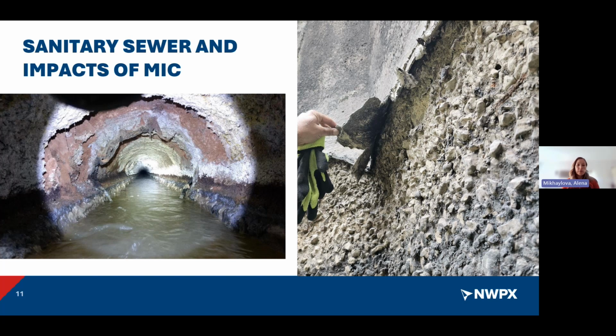Here are other examples that we obtained from some municipalities. The one on the left was a sewer line discovered during one of the CCTV inspections. It was a St. George location. As you can see, some parts of the pipe were completely gone. You can see some soil visible. In some instances, this could be a catastrophic failure, especially if it was under a highway. Luckily, it was not, and there was no collapse of this particular structure. But this pipe severely deteriorated. Also note that the majority of the corrosion and deterioration happened on the top half of the pipe. That's where the gases rise and settle on the walls.